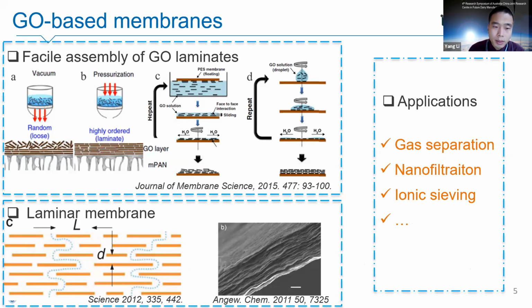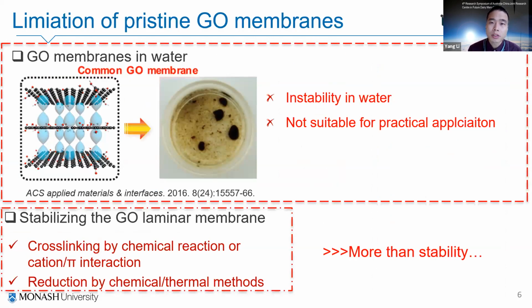As shown here, the laminar membrane has some unique properties. It includes nanosheets with some interlayer spacing. The water usually goes through this membrane's tortuous pathway, and the sieving comes from the interlayer distance, something we describe as the size sieving effect. But one thing that has limited the GO membrane separation is the swelling property of graphene oxide in water. As the GO membrane is unstable in water, it's not really practical for industrial applications. One thing we can do is to stabilize the GO by cross-linking or chemical reduction or thermal reduction methods.